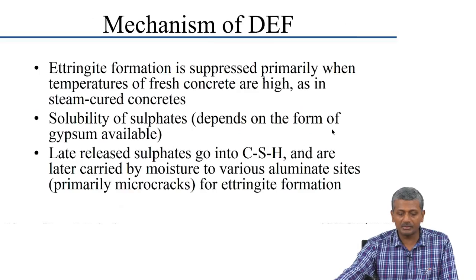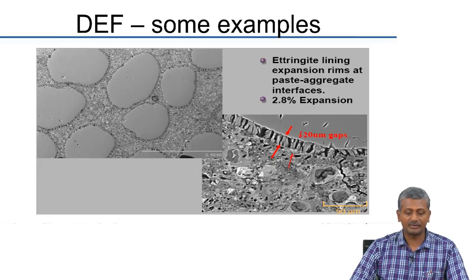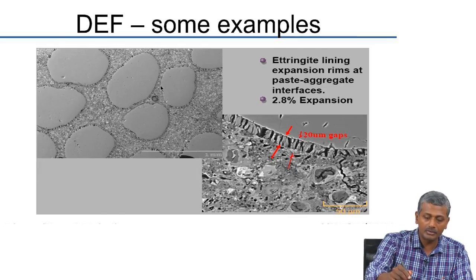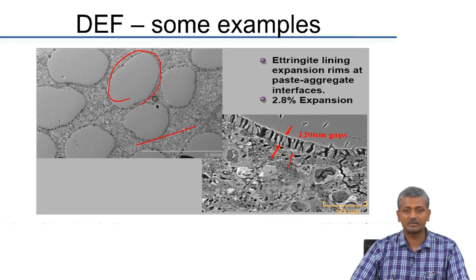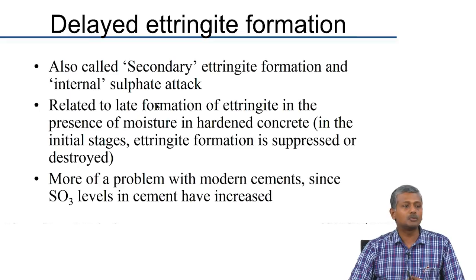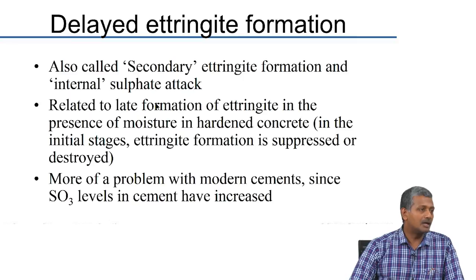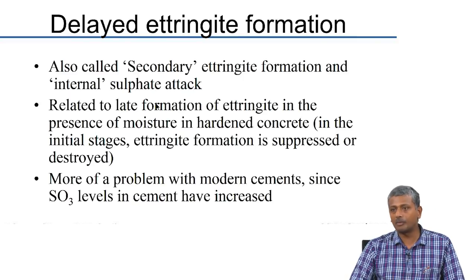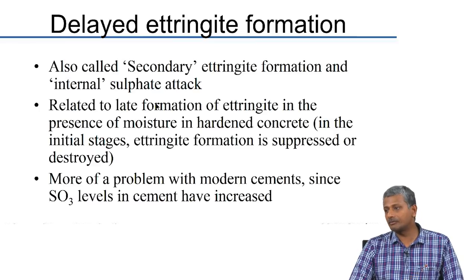At the interface between cement paste and aggregate, a lot of ettringite is deposited, visible around several aggregates. This was detected in microstructural study, and the conclusion was that this ettringite had reformed in the system after the concrete hardened, because it could not form in the initial stages. This initial-stage suppression of ettringite formation happens primarily because of heat curing — when you provide very high heat to the system, generally temperatures above 70–75 degrees Celsius, formation of ettringite gets suppressed.